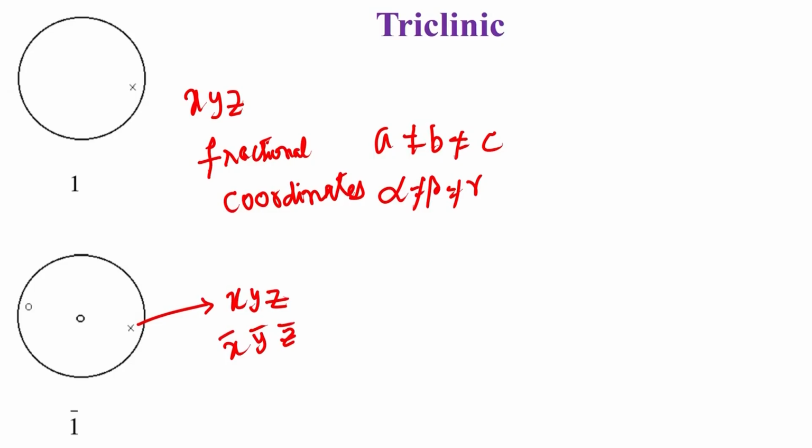We can also put in another piece of information on this slide, and that is the information about the Bravais lattice. We have already seen the 14 Bravais lattices in an earlier class. In the case of triclinic systems, because there are no rotation axes and no plane of symmetry and so on, no other possibility is there except a primitive system.